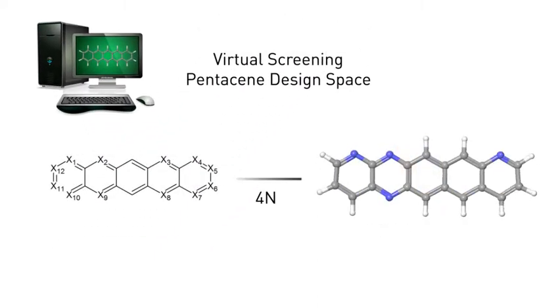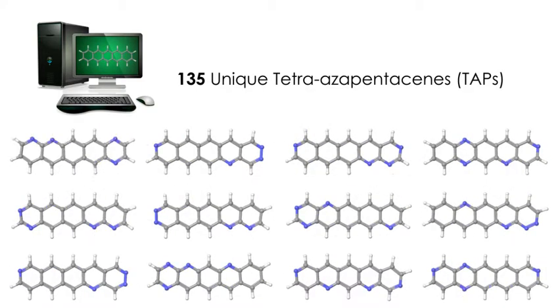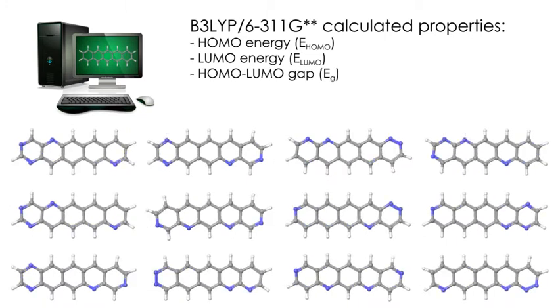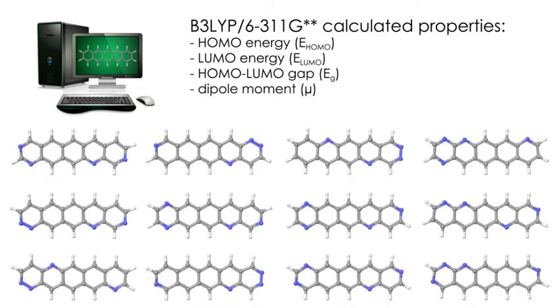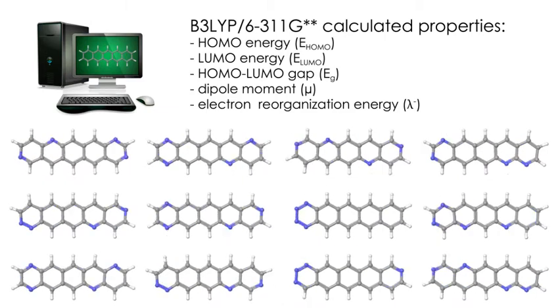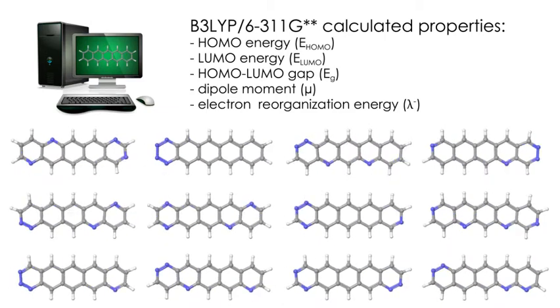Here the pentacene framework undergoes automatic substitutions of four nitrogens resulting in 135 unique tetraazapentacenes, each of which have their HOMO and LUMO energies, HOMO-LUMO gap energies, and dipole moments automatically calculated. Electron reorganization energies are computed for leading tetraazapentacenes.